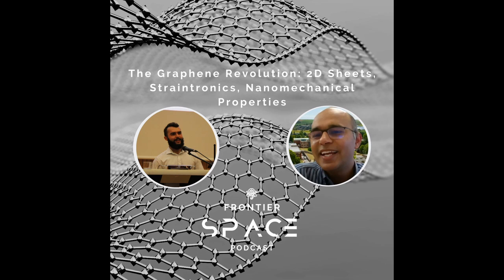It is a recent work that we have published in Small. We have done texturing, but we changed the periodicity. For example, in one case the grooves are very close to each other, let's say 40 nanometers, and then we gradually increase the spacing of the grooves. And then we deposit single layer graphene on it. So wherever the groove separations are smaller, with low periodicity, the graphene has one kind of strain. And where the periodicity is higher, it has another kind of strain. And this strain is permanent because the textured samples are irreversible. So we generated the same silicon and same graphene with different strains. That's a very good example.